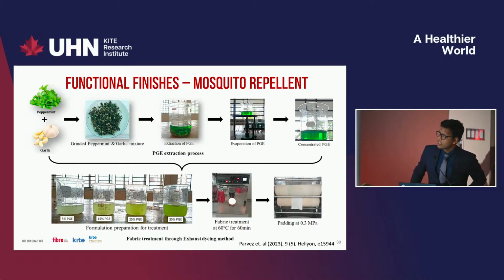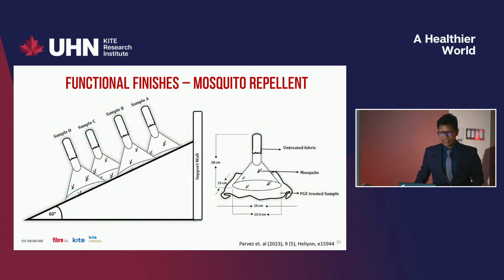I'm going very fast here because we are running out of time, but we used peppermint and garlic extract together. In the literature, people used peppermint alone before, so we wanted to see how the combination with garlic works. We used a tiny percentage of garlic. We prepared 4 different samples with different concentrations, up to 35% concentration of our extract, which is a combination of peppermint and garlic. We did 2 tests. One is the WHO standard cone test, and another I'll explain later.